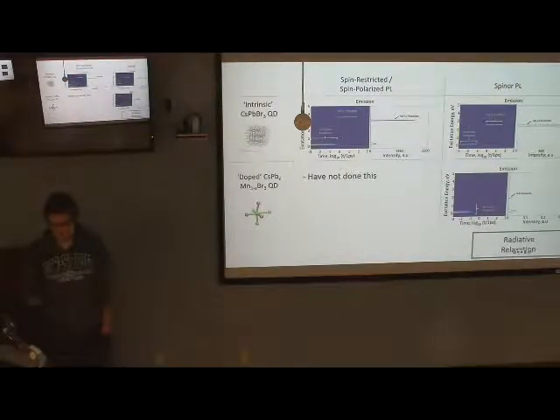And for the same region in the spinor calculation? I can't even see it. For intrinsic and spinor, this orange stripe ends at around 15 picoseconds. Is there a way to continue it? It's with maybe frozen propagation. Yeah, it's a work in progress. Okay. Because this cutoff here is artificial. Its radiative lifetime should be longer, but it's just a bug of our code right now.